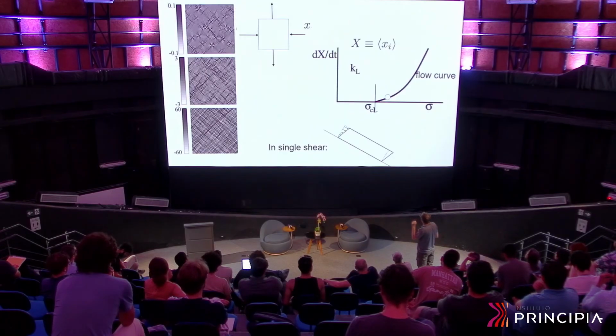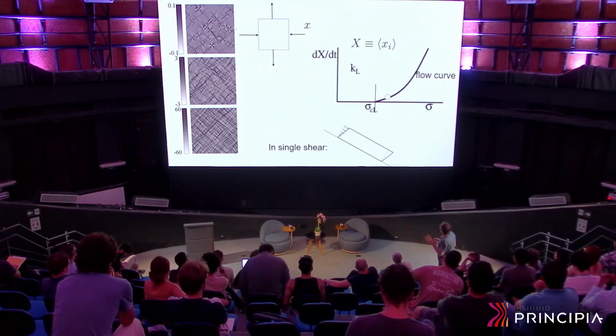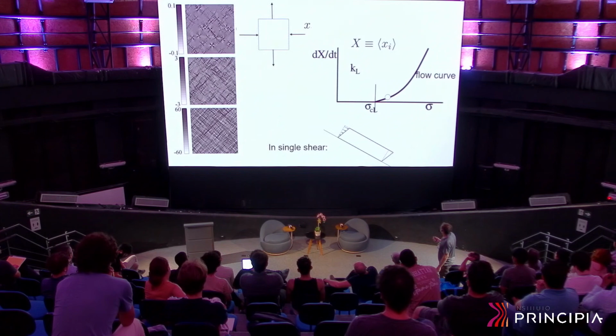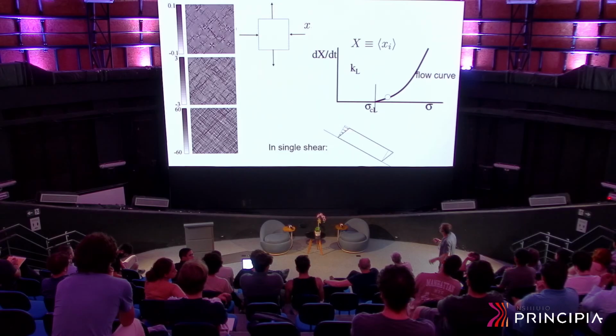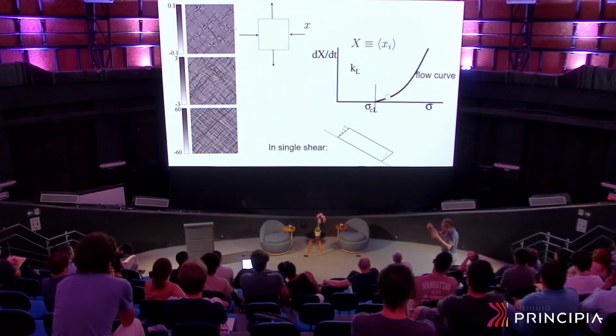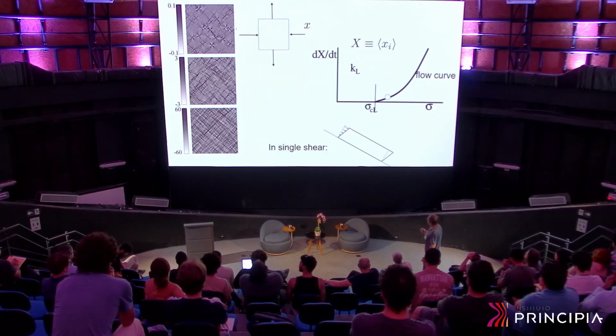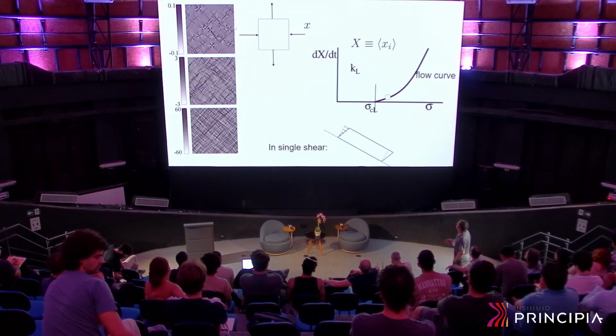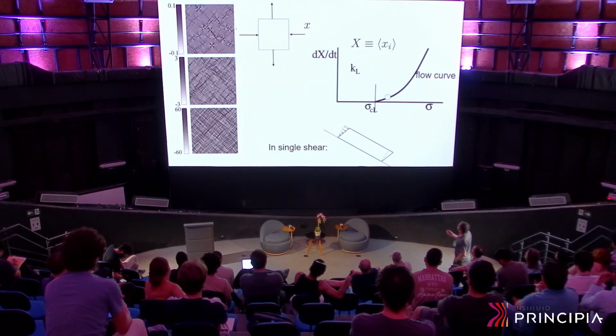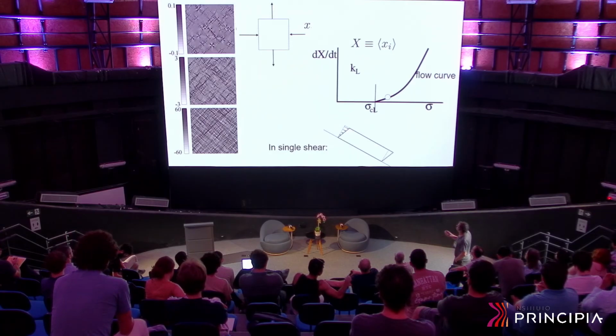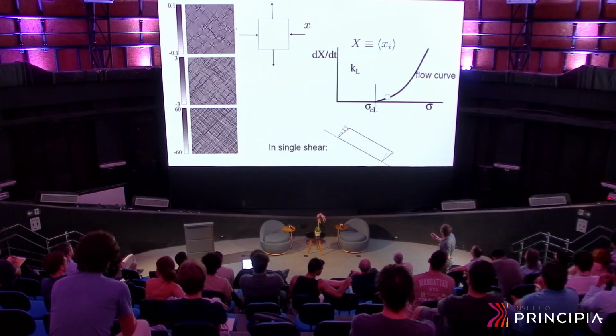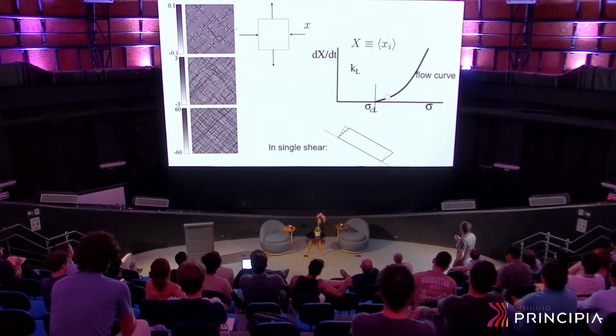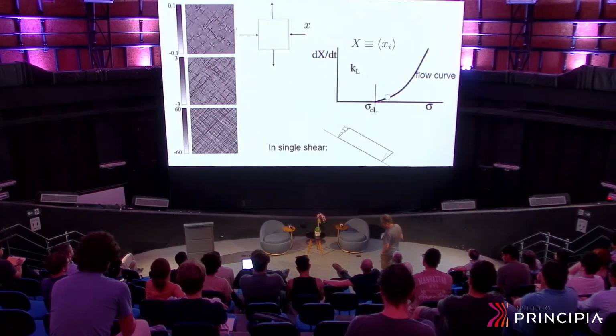Actually, one point to be clear about: the simulation that I will present for the yielding model will not describe the full situation at every horizontal plane, but will describe the situation in a given spot of the material at some depth, and they are homogeneous simulations. They do not describe the full situation all across the system. But the important thing is that in any case, in this material, whatever x is, and as for this case, x is the strain deformation in the system, the velocity of deformation, this large X is the average of x over the whole system, as a function of the stress, has in fact the form of a yield stress material with a critical stress that is given here.